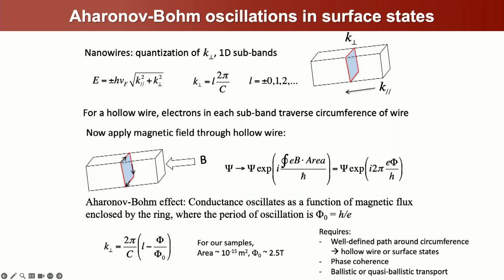So, this should easily differentiate between whether your conductance is around your surface states, where you have a well-defined path, or whether it's through the middle, where you have many paths that will average out to zero. Okay. You also require phase coherence. This is another property that you should have. If you have lack of backscattering, you should have a pretty clean system that's phase coherent. To see these oscillations, you need phase coherence, and you need ballistic or quasi-ballistic transport.